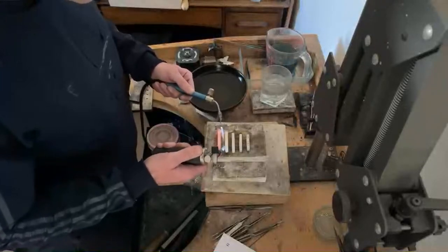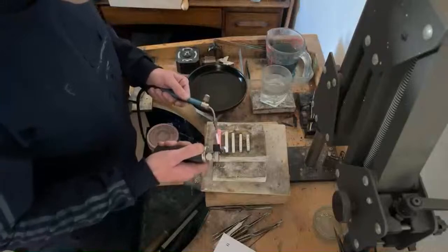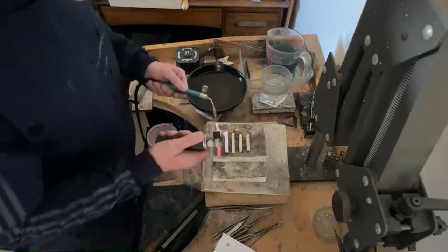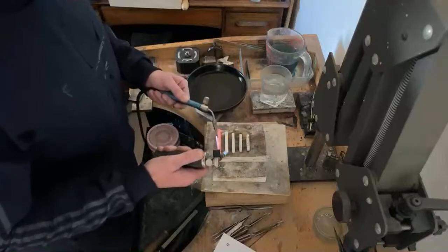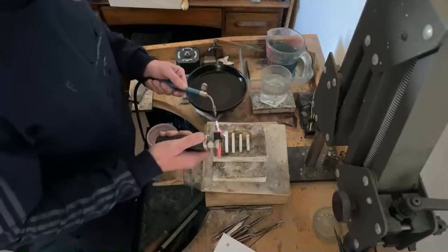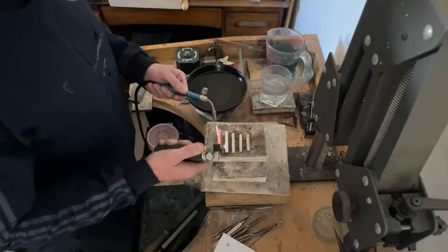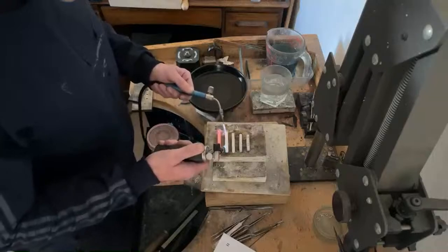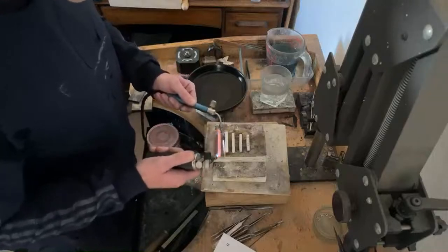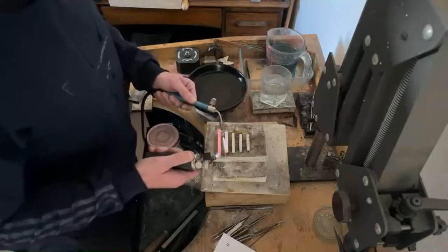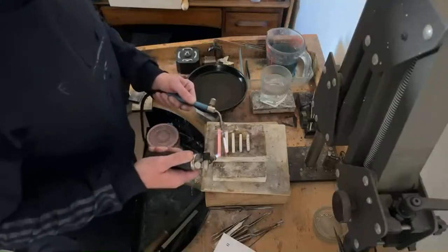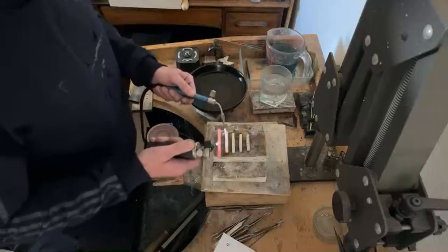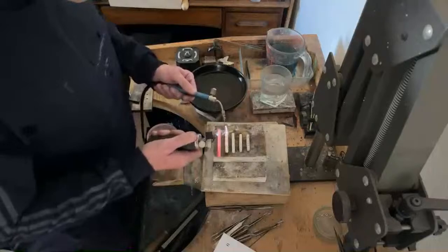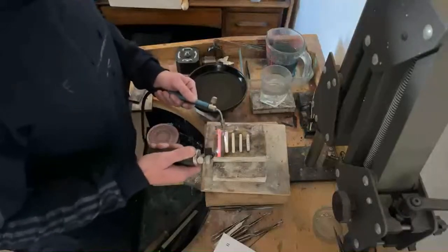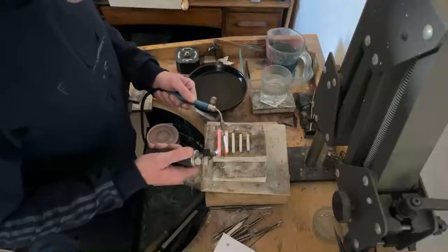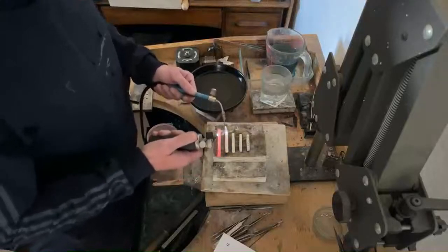Yeah, obviously it's not good for the rolling mills, wringing out your sponge-like ingots, and that is the reason why I remelted these, because it was actually quite bad on the last batch. I don't know what I did with them, but every time I put them through the rolling mills, I was having to wipe them off, and it didn't diminish. It wasn't getting worse, but it wasn't diminishing as they compressed down, and I was getting this weird black silver oxide coming out of them.